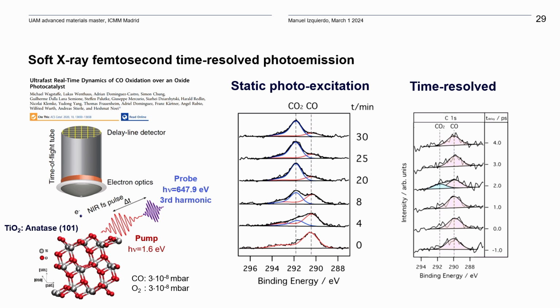However, if you put in photo excitation, even if it is static, what's going to happen is that as a function of time, you will have the formation of CO2 due to the oxidation that is photocatalytically activated. Then they did the time-resolved experiment, and what they saw is that at the beginning you have only CO.